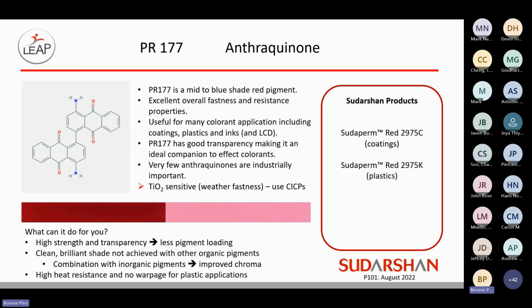One thing to note when using this pigment is TiO2 sensitivity in weather fastness. TiO2 has high photo degradation, and pigment red 177 chemistry is susceptible to that. So one way around that is to consider using a CICP, like a pigment yellow 53, to get that light fastness or weather fastness, as well as a good hiding aspect of it.